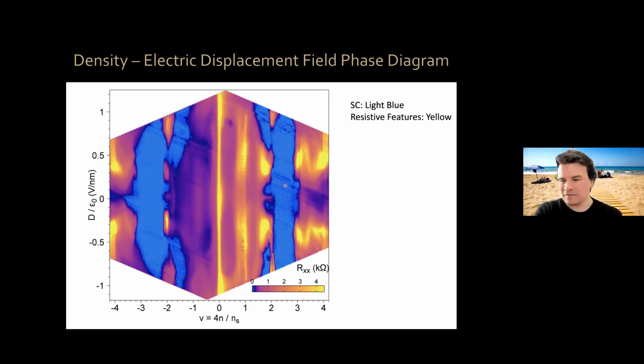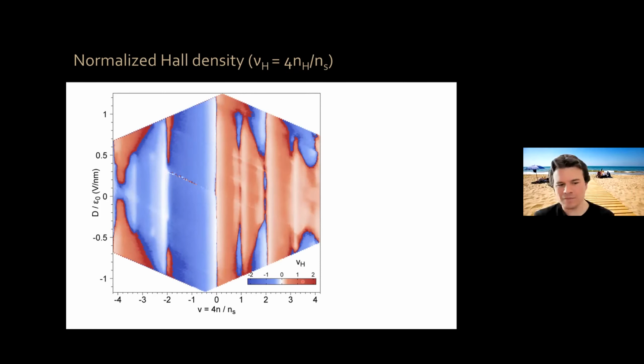Now, because this diagram is quite complex, we can try to measure other properties, not just resistivity and superconductivity, and see if we can correlate them with these features. In particular, the thing that I'm going to show you is the normalized Hall density. The normalized Hall density is the equivalent of the filling factor for the regular charge density. So it's 4 times the Hall density divided by the superlattice density, these 4 electrons, 4 holes per moiré unit cell that I mentioned earlier. Now, the Hall density is proportional to 1 over the Hall resistance, so that's important to take into account. So this is the normalized Hall density as a function of, again, filling factor and displacement field. And as you can see, it's also a relatively complex phase diagram.